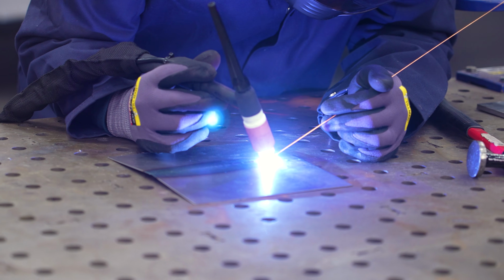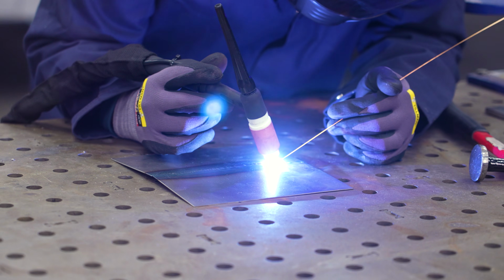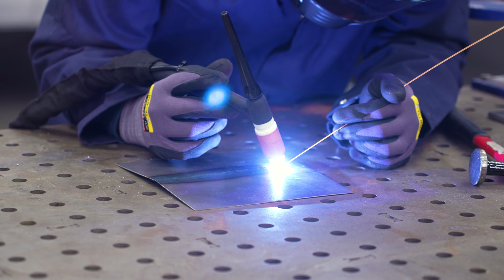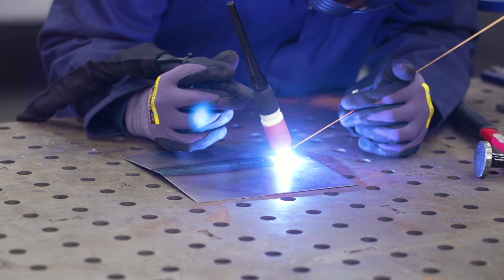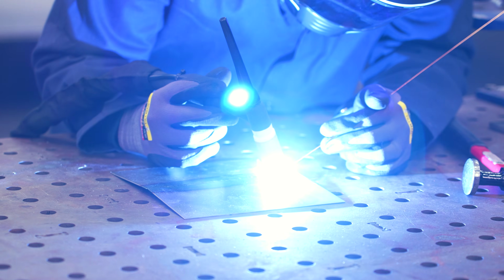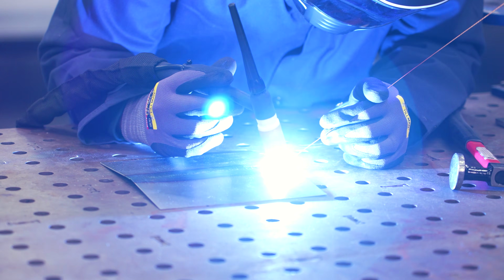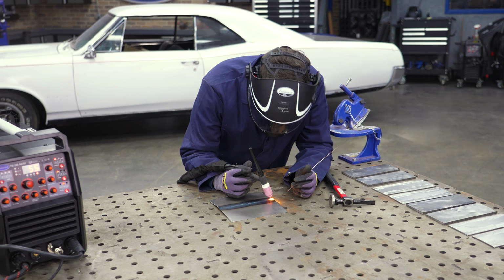If I were to weld this with no pulse, I would have to use a lot less amperage, have to move a little bit quicker, and it also would be a lot less consistent because the faster you weld, it's very hard to keep it very consistent. Bring it up to the edge here. Oh, see, I blew through the end. You'll have that on these bigger jobs.